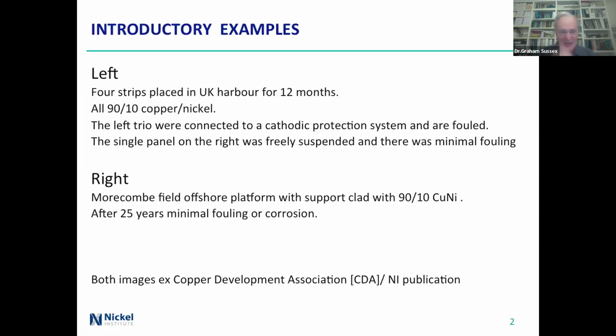On the right, it's an offshore platform, and they clad the supports with 90-10 copper nickel - 25 years in service, with minimal fouling and minimal corrosion. Both of those images come from a Copper Development Association Nickel Institute publication.